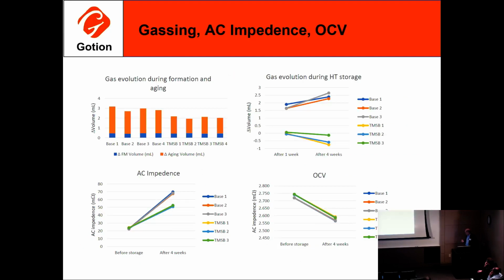And this is the same type of analysis that we look at. So formation gassing, which are the blue squares at the bottom, we pretty much got that under control now for the LTO system, which is a big challenge. And now we're working on gassing coming from the orange bars, which are at high temperature storage. So that's what happens after aging. So you're getting gas formation. So obviously we're here at the beginning and we're working our way down on that.